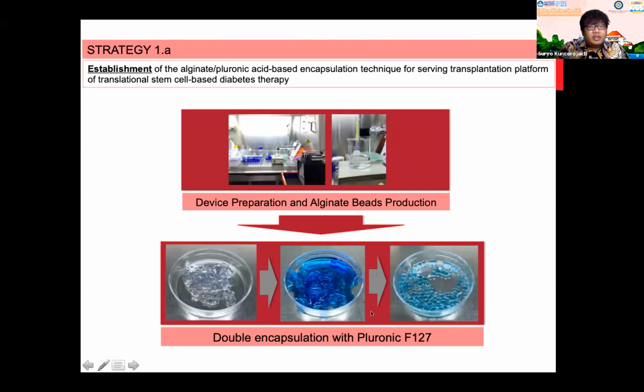In this part of the study, the device preparation and alginate bead production were performed. To obtain the alginate beads, the nozzle extrusion method was employed. It can be done automatically by the utilization of a peristaltic pump. Here we can do it automatically, or we can just do it manually by hand. And the produced alginate here is then treated with the blue solution here. The blue solution here is a pluronic. I use methylene blue to give the pluronic a color. In the normal form, the pluronic is transparent and colorless.